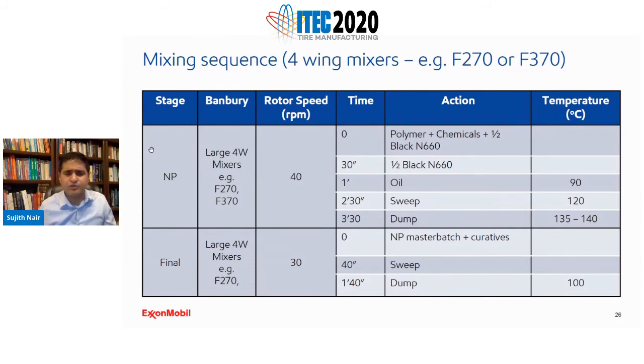One thing that I'd like to point out before going into this mixing is that X-Pro will mix the same way as bromobutyl mixes. So if there is a specific mixing pattern that you're using for bromobutyl, you don't need to change anything for X-Pro specifically. This is one of the mixing procedures that we have used as a standard, and we have used this for all the polymers. So we have a two-stage mixing. One is a non-productive, one is a final, and basically the non-productive is in a big Banbury in an F270 machine,